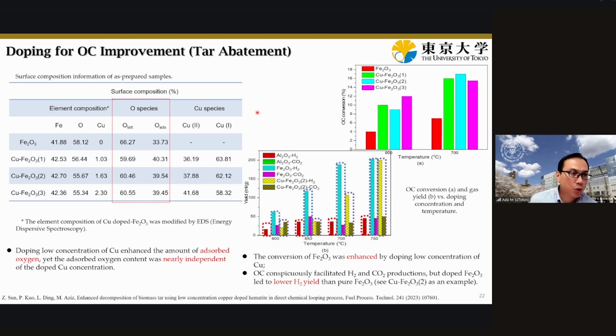Our study showed that we can classify the oxygen in oxygen carriers like Fe2O3 into lattice oxygen and adsorbed oxygen. And you can imagine that when we dope with copper, we reduce the amount of lattice oxygen while increasing the adsorbed oxygen. What we can see here is that the energy for the lattice oxygen is higher than for the adsorbed oxygen. So if we would like to release oxygen from the oxygen carriers, we prefer a larger ratio of adsorbed oxygen. I mean, we can reduce the activation energy for the reaction itself.